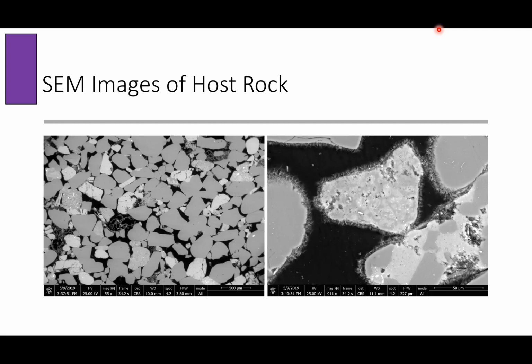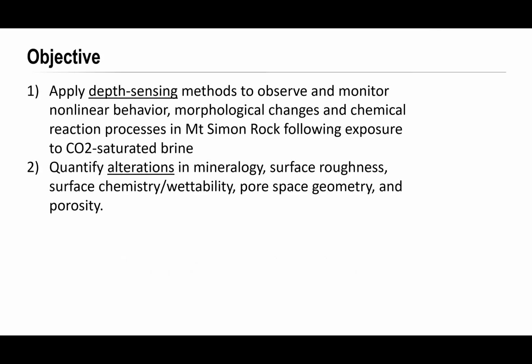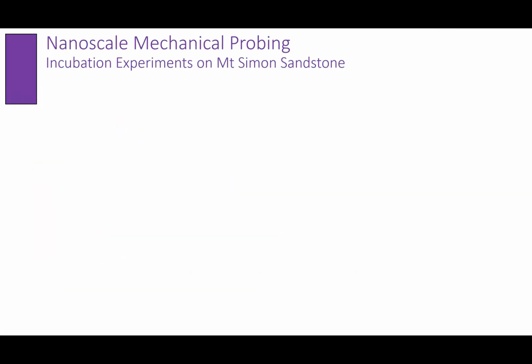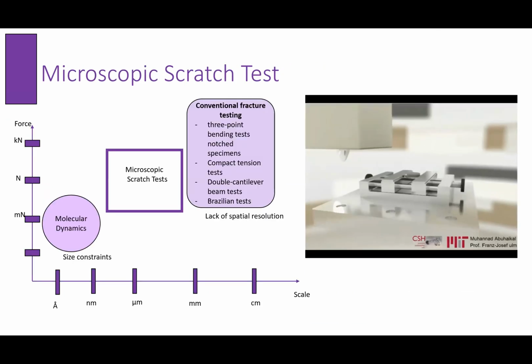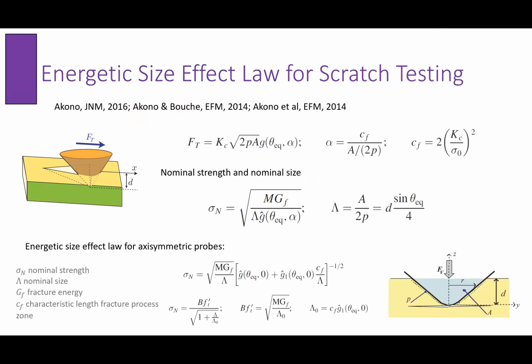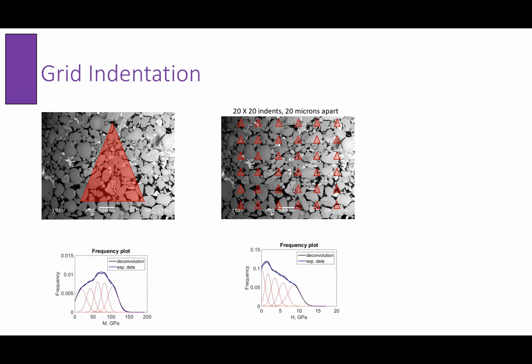One way to do it is actually to just see that the indentation is going to be anisotropic, and that way you have a tensor. Because right now my indentation is only in one direction. Versus in this case, we would have indentation in at least 2 directions. And that way we have a tensor in 2 directions, and then this time I just expand the space, because currently when I did my statistical deconvolution, let me, sorry, this is not the easiest way of doing this, but I'm going to get there. When I do my statistical deconvolution, I only have 2 axes. So I have an M and H.